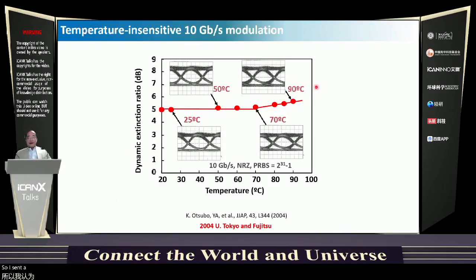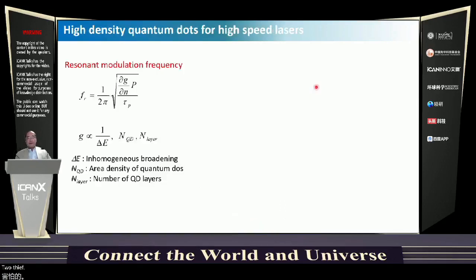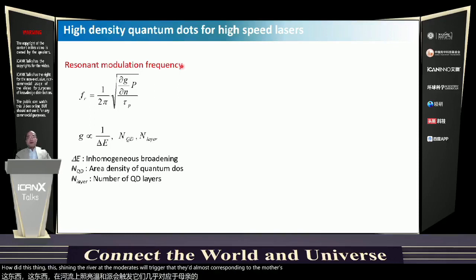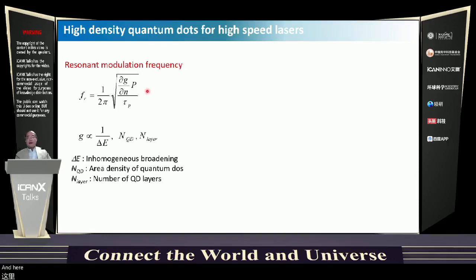So at that time, we also demonstrated the temperature insensitive 10 Gbps modulation. So we realized high-speed operations in the temperature range from 20 degrees Celsius to 90 degrees Celsius. This expression is the resonant modulation frequency. That is almost corresponding to the modulation speed. And here, the gain plays very important roles. Exactly speaking, differential gain is placed here.